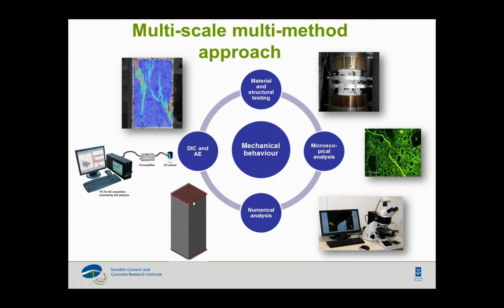In terms of the behavior of concrete in compression, we did a compressive test. We looked at the modulus of elasticity. We got the entire stress-strain response of these specimens, and we tried to use digital image correlation in a very innovative way to identify how the stiffness of concrete is changing in the concrete cover. We also used acoustic emission to evaluate the damage. So the acoustic emission and digital image correlation were used together to understand the distribution of the damage across the cross section.